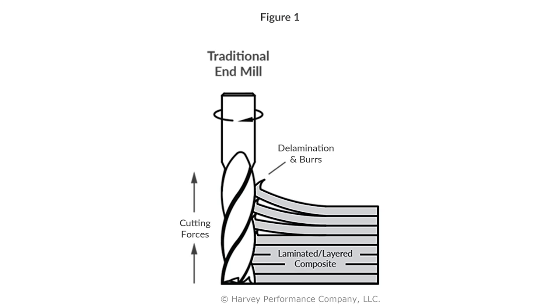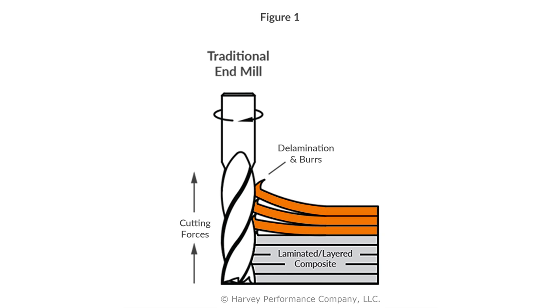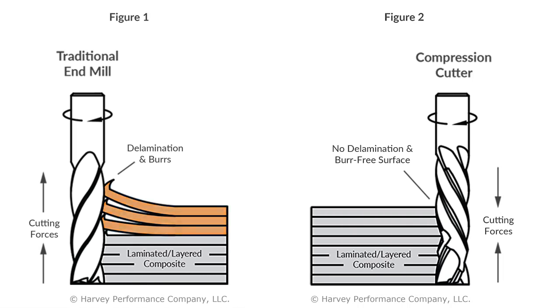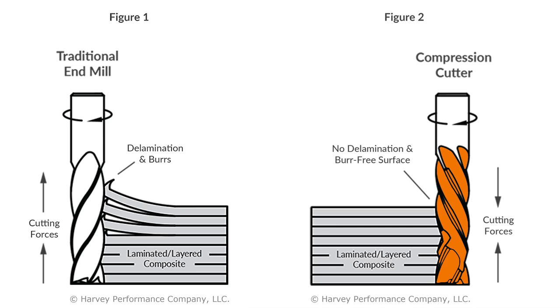With a traditional end mill, two things are happening. The end mill is trying to pull the work up out of the work holding or vise, and likewise, the effect of the cutting pressure is also trying to pull the tool out of the spindle or tool holder. The consequence with a laminate type of material is it will delaminate. It will start to tear apart, and that's exactly what compression cutters solve. You're having the bottom portion of the tool cut upward, and the remaining portion of the tool cuts downward. It compresses those pressures toward the center, which avoids or solves the delamination issue. For a compression cutter to work, you have to have sufficient axial depth of cut to cover that range where the tool helixes have blended together.